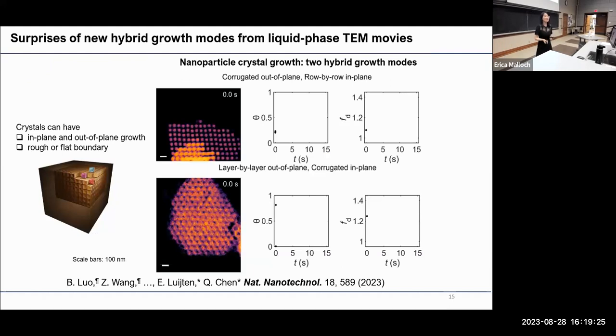This is the beauty of direct experimental imaging. It can help you go beyond theoretical expectation. In retrospect, it's actually pretty straightforward. You have a three-dimensional crystal, which means you have at least two growth directions, the in-plane growth and the out-of-plane growth. For each growth direction, you have two choices: you can be flat or rough. As a result, you should have four growth modes, and our experiments were able to observe all four growth modes.